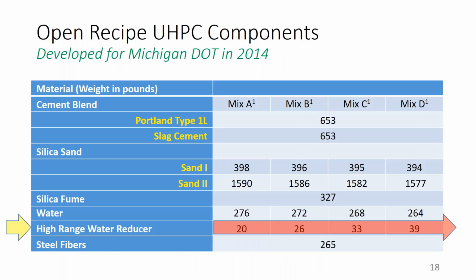Now, this is the mix that was developed for the Michigan Department of Transportation in 2014. It has been used now in numerous projects and is the basis of many mixes that developed around the country, the non-proprietary mixes. So you can see that it's made up of cement, slag cement, two types of sand. Remember where I mentioned one particle fits inside the others, silica fume, water, and a high range water reducer. And of course, the steel fibers.